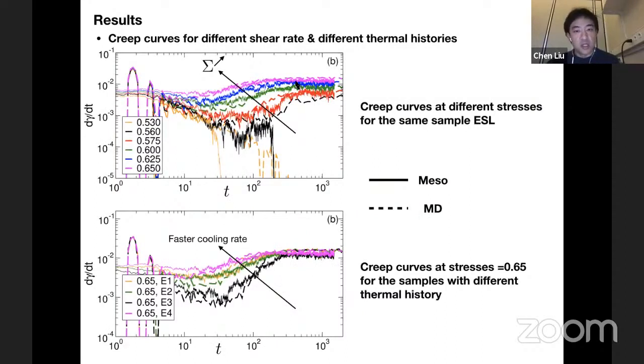So here in the first figure, I show the shear rate as a function of time when you apply different step stresses to the same sample. The second figure is the creep curve for the same applied stress, but for different cooling rates. And you can see that, within some fluctuations, the meso model captures the MD data relatively well.